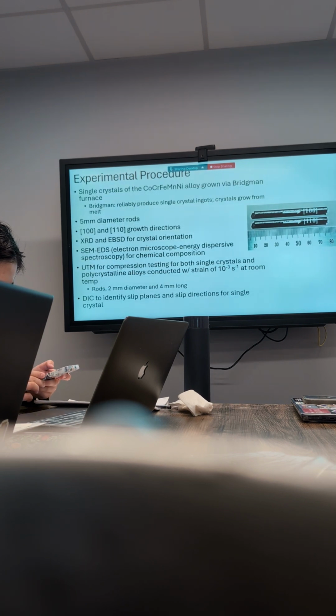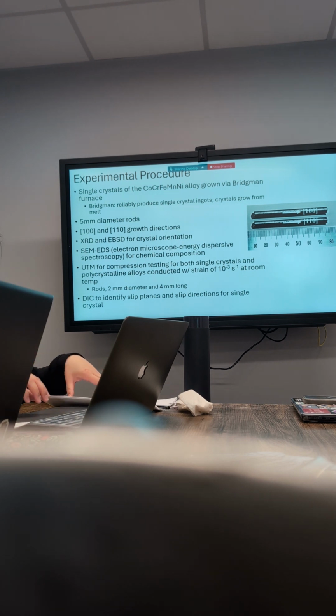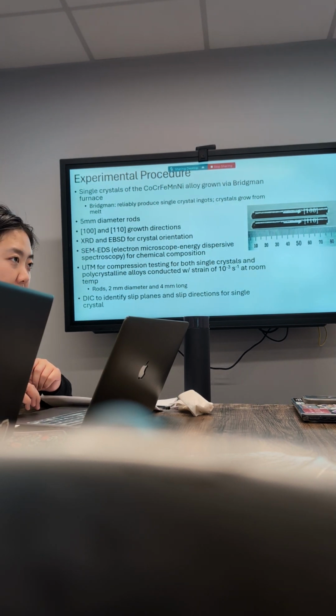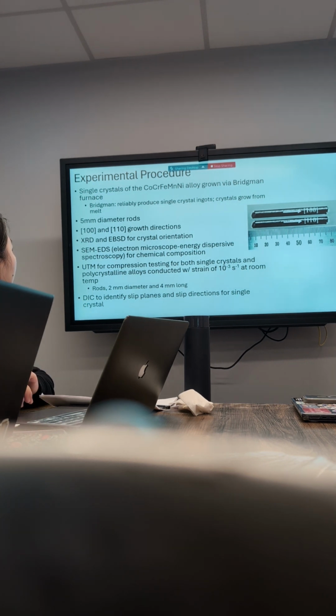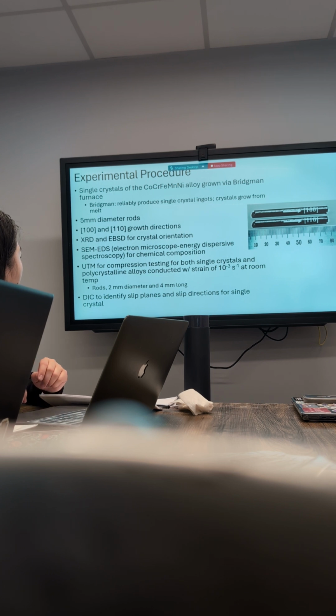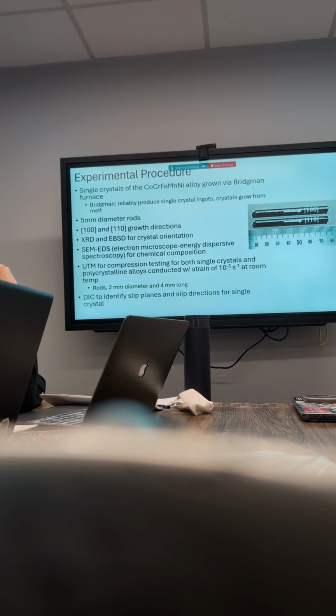So for their experimental procedure, they use the Bridgman growth method, which actually is how a lot of ferroelectric and piezoelectric perovskites are made, which is interesting. It reliably produces single crystals, specifically ingots, and you can see that they clearly are making these rods. They grow from melt, so it's high temperatures, good purity. They made 5mm diameter rods in 100 and 110 growth directions. They used XRD and EBSD for crystal orientation, SEM for chemical composition, and then a UTM, which is a mechanical testing apparatus for compression testing.